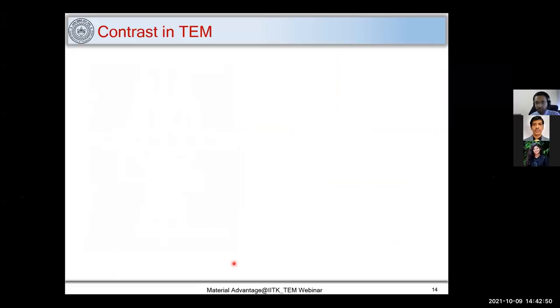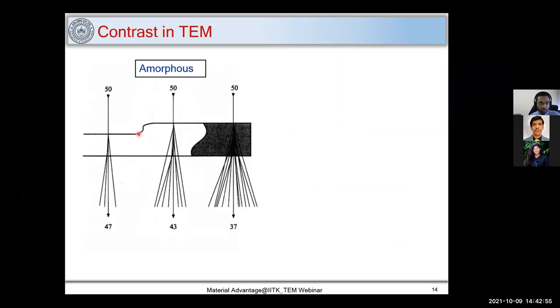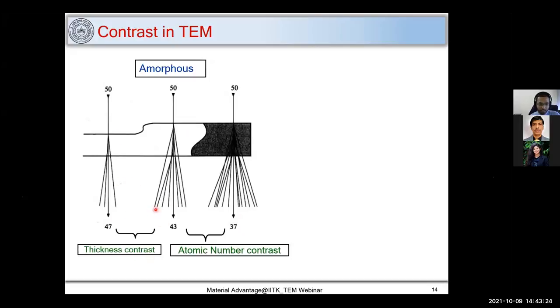Now coming to contrast in TEM, let's consider an amorphous material. Here you can see the thickness is varying in these two cases. Where the sample is thin, you have more intensity coming out, whereas where the sample is thick, you have smaller intensity coming out. Now in this case, the atomic number is higher. So you can see that even though the thickness is the same, the intensity coming out is smaller. This kind of contrast is called thickness contrast, and this kind of contrast is called atomic number contrast.